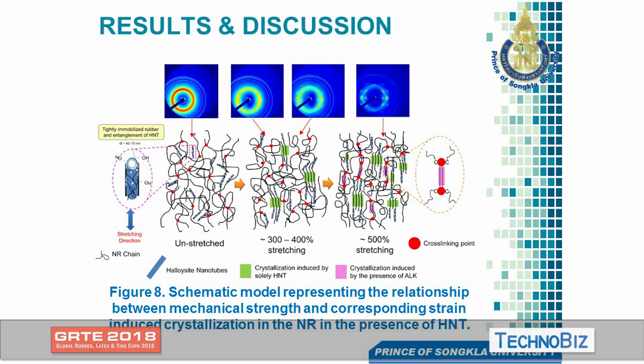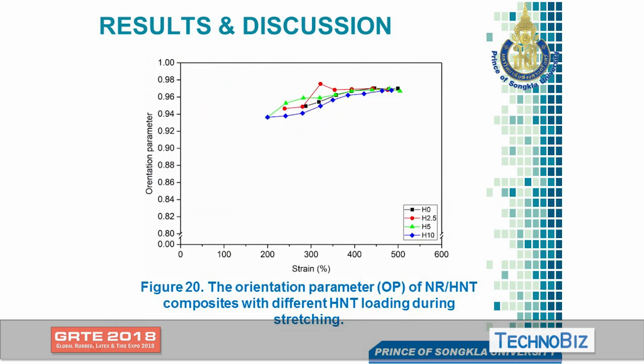So basically, it's like HNT. Without HNT, this kind of thing happens at higher deformation. Once we include the HNT, it's like HNT can rearrange together with the molecular chains once the strain is applied. Due to the better dispersion and compatibility between HNT and natural rubber, it can enhance this kind of effect. So that means HNT can improve strain-induced crystallization in natural rubbers.